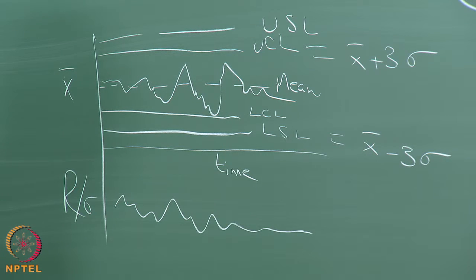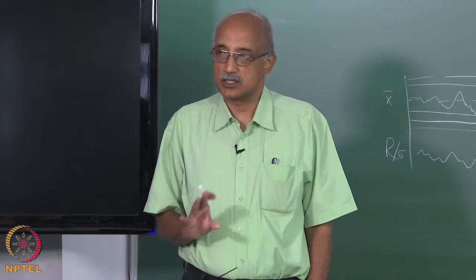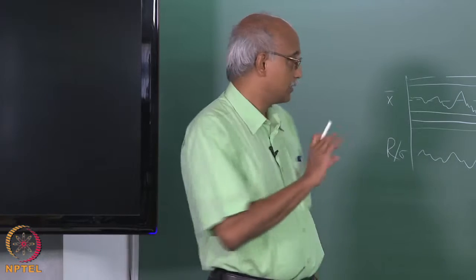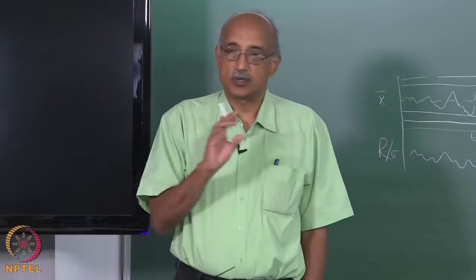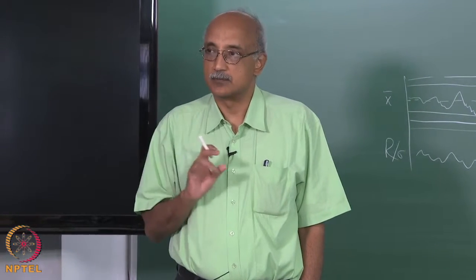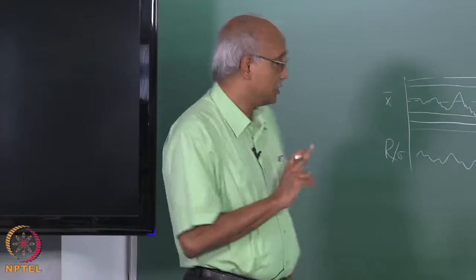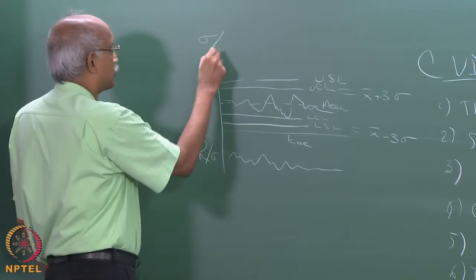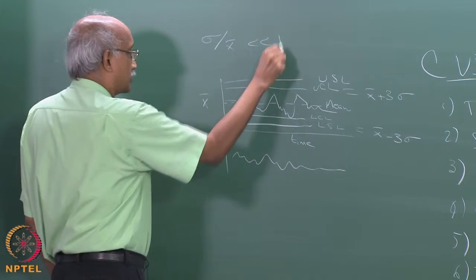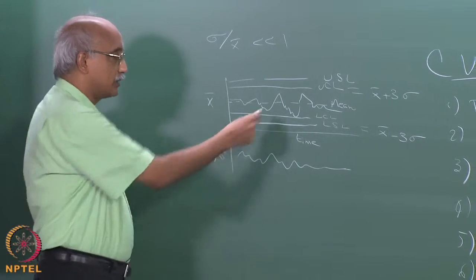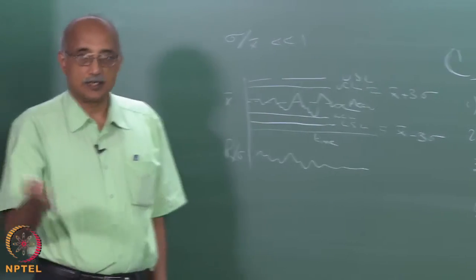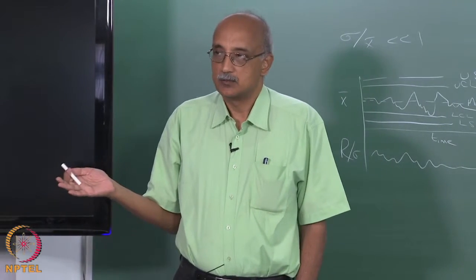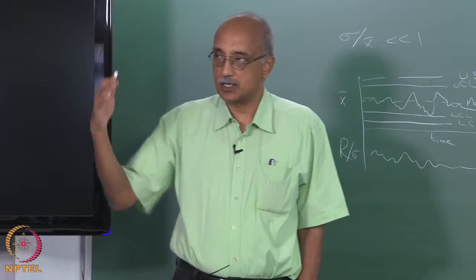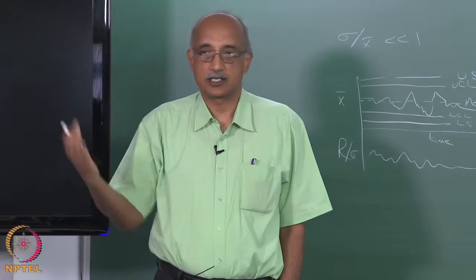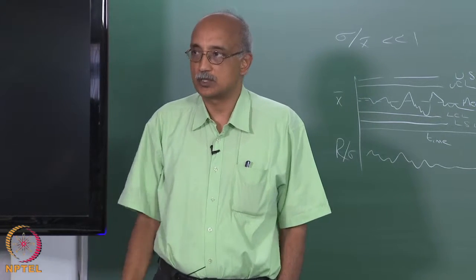So when people talk about Six Sigma quality, what they are talking about is this kind of methodology where you try to essentially maintain your process within plus or minus 3 sigma. But the inherent assumption here is that sigma over X bar is much smaller than 1. This whole thing will break down if your standard deviation in the process is very high, because then your X bar plus 3 sigma can actually exceed your upper control limit, and X bar minus 3 sigma can exceed the lower control limit.